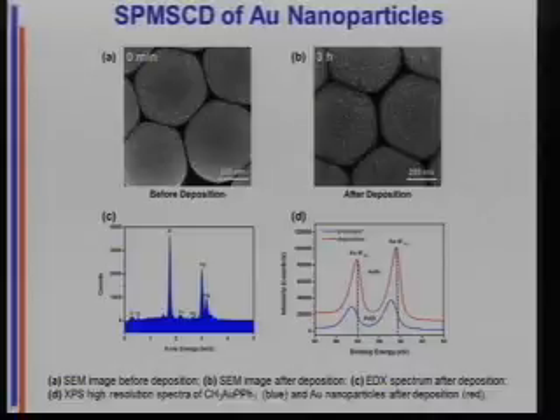So before deposition, this is an SEM image of the substrate. Okay, it looks like little cauliflowers. After the deposition, it looks like little cauliflowers with white spots. Those spots are gold nanoparticles. Okay, we can characterize those. Okay, here's the XPS. We can see the precursor XPS is gold 1. The nanoparticles are gold 0. Okay, there it is in the EDX spectrum.